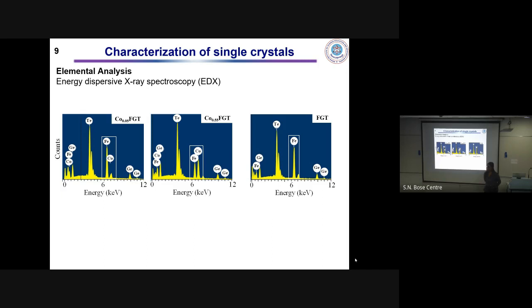During this process, what I have observed is that even if I take extra iron during the CVT, it depends on a lot of conditions. My crystal growth experience tells me that even if I take some extra iron, it doesn't confirm that I will get the proper concentration, because I have tried on a number of crystals. In CVT, it takes atom by atom.